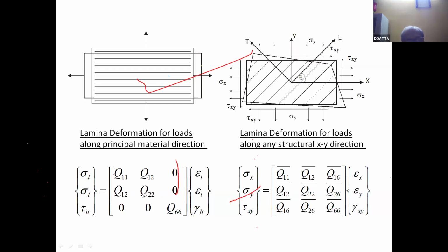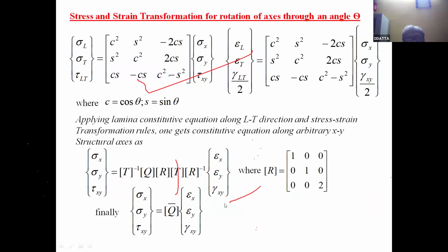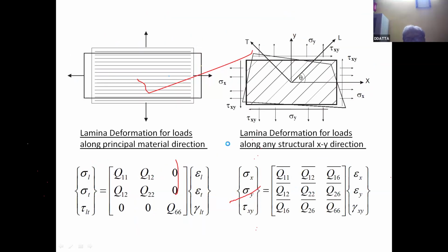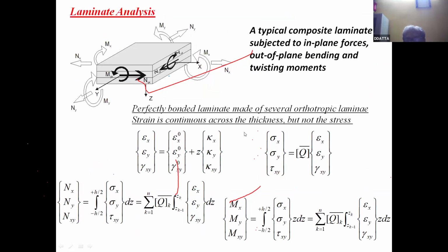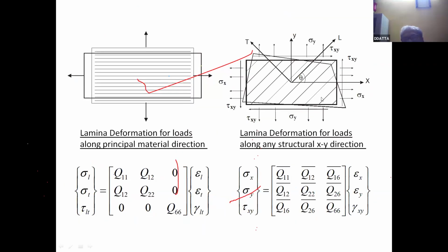And compared to that, as I said earlier, when it is the L and T directions, then the matrix is not fully populated. These elements are zeros. But here it is fully populated. It means that even if you apply only sigma x, there will be epsilon x, epsilon y, gamma xy, all strain components will be developed. And how are they related? They are related by these transformations. So the Q bar matrix can be generated from the Q matrix. Okay, so this is the scenario.